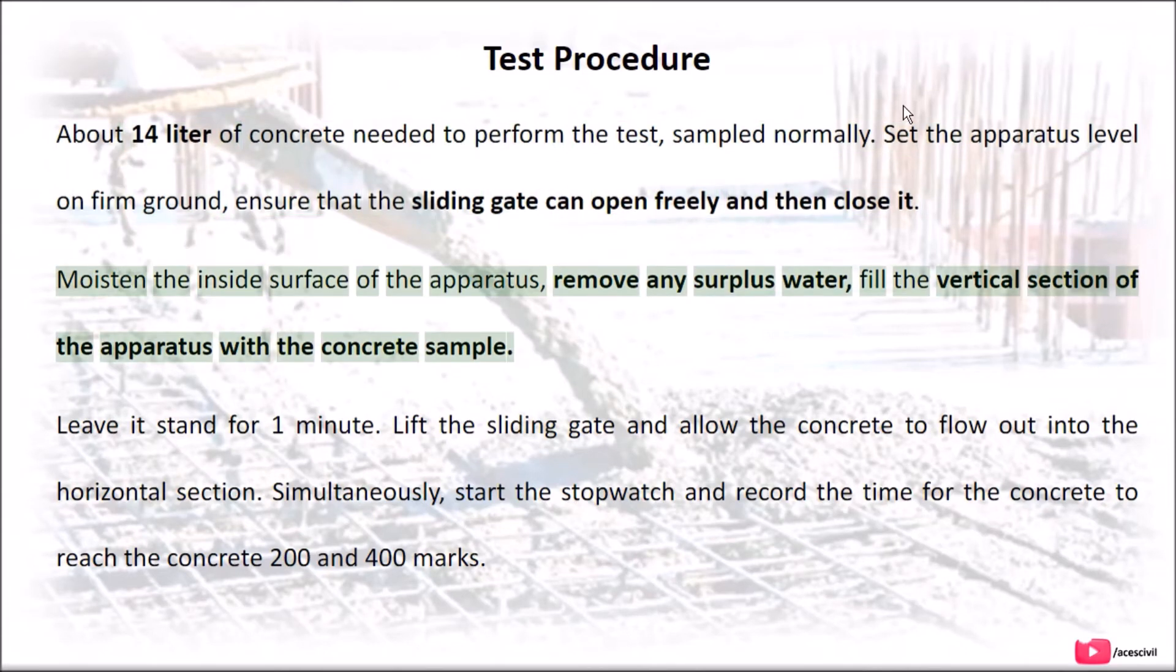Moisten the inside surface of the apparatus, remove any surplus water, fill the vertical section of the apparatus with the concrete sample.